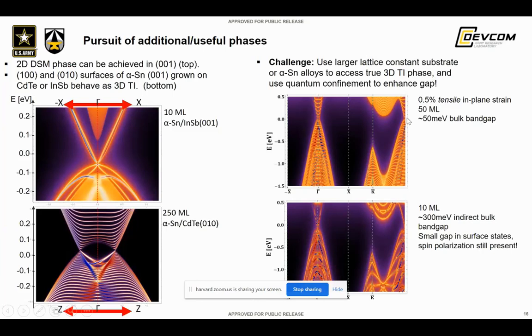You can use that to see large band gap materials such as 50 meV at 0.5% tensile strain using a thickness of 50 monolayers. And if you go down to quantum confinement with 10 monolayers, you can open up a fairly large band gap, an indirect band gap nevertheless, in this material. And so this is quite interesting. Experimentally, we're going to try to see if we can realize this. This is a theoretical prediction from this work.